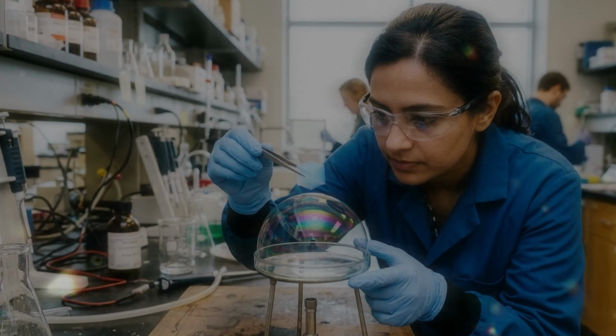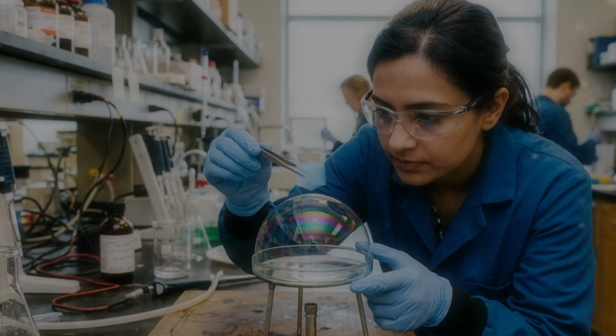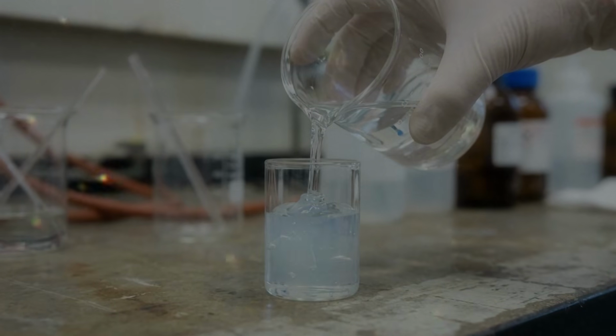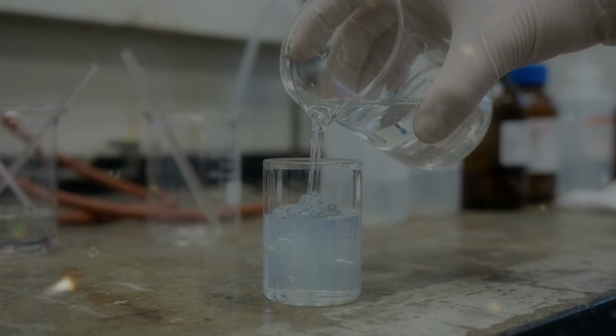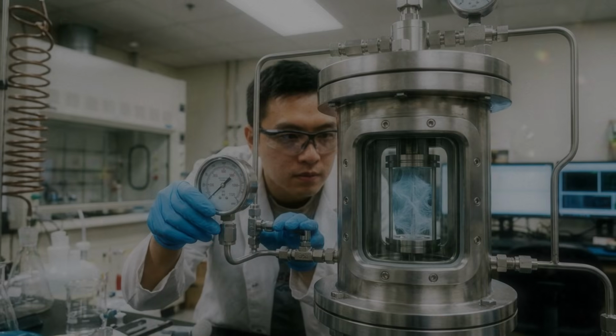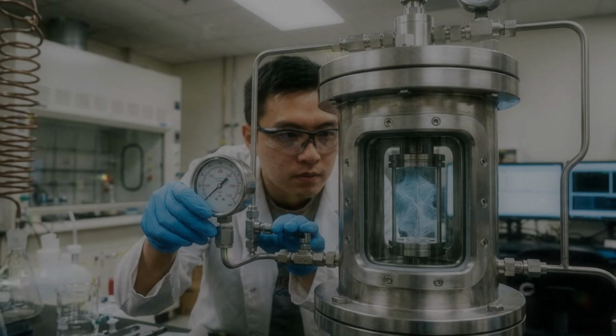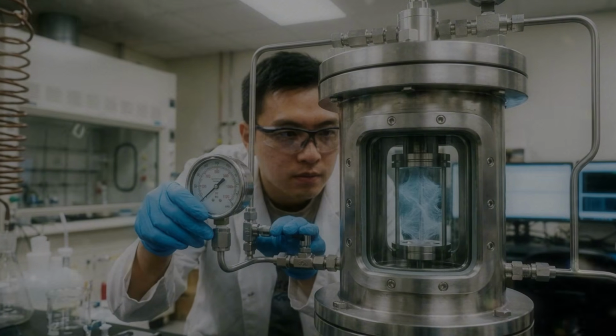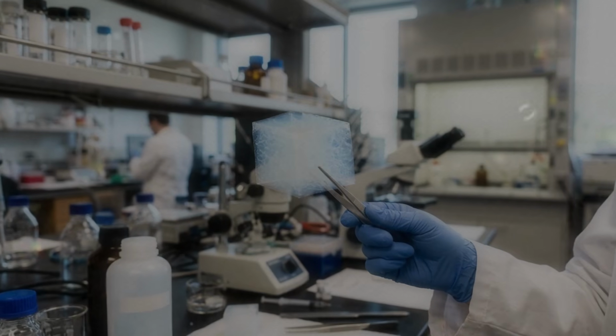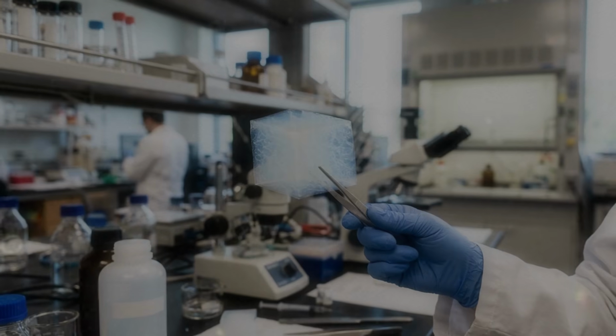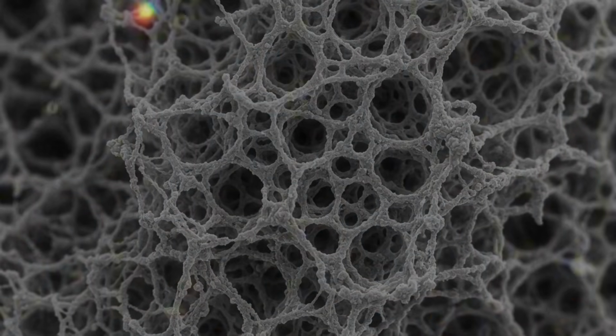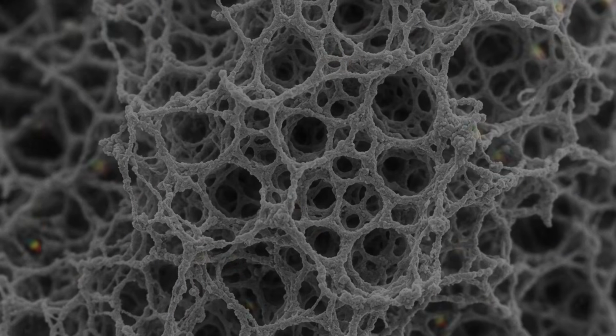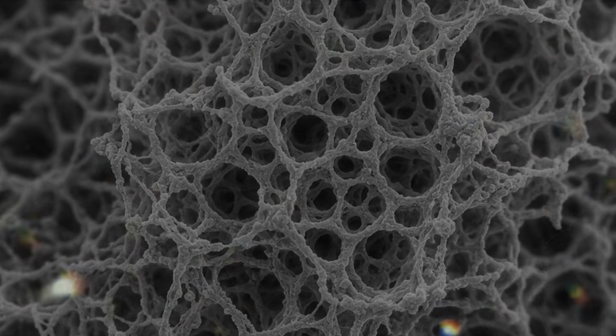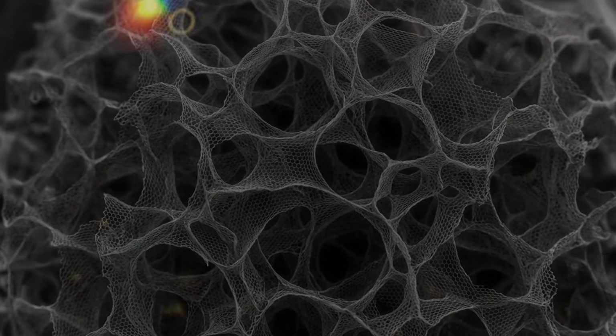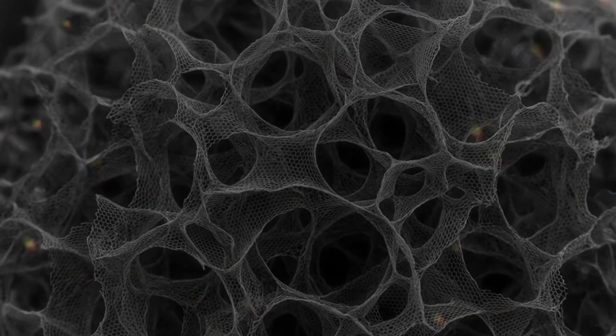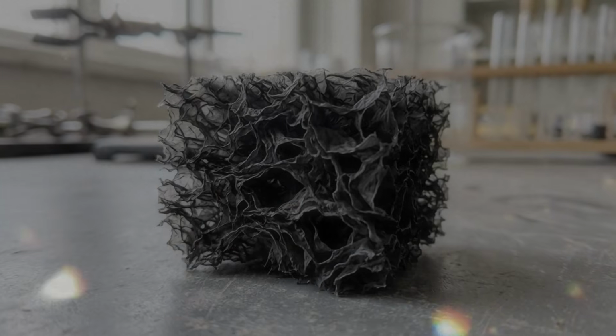For the moment, the important point is that an aerogel is not created by drilling millions of tiny holes into a solid block. The pores develop as part of the gel itself. The solid network forms around liquid, and the liquid is later replaced by gas while much of the network remains in place. This explains why the pores are so deeply connected to the identity of the material. They are not damage, decoration, or empty space added afterward. They are part of the original architecture. Remove the pores by crushing the sample, and many of the unusual properties disappear. The chemical ingredients may remain, but the material is no longer behaving as the same aerogel.